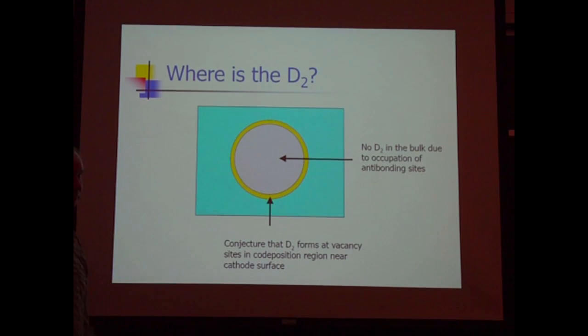Because the original cathode is pure, and the surface has those impurities, you can separate the original cathode from what was co-deposited. Well, certainly the interior also has platinum and other stuff at ppm type levels, but the amount at the surface is much, much greater. So it's completely clear from this interpretation, which is not the interpretation that's made in these analytical papers. So this is my interpretation. If I interpret it this way, then I can tell exactly what regions co-deposit just by looking at the trace of what it is that's on the surface.